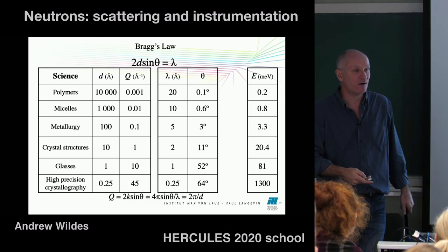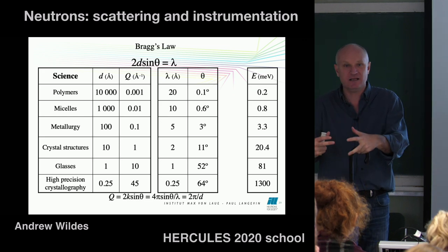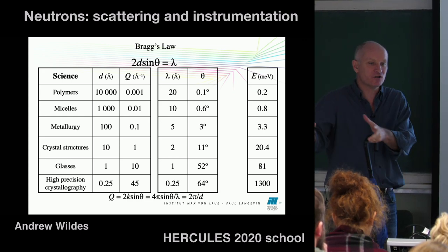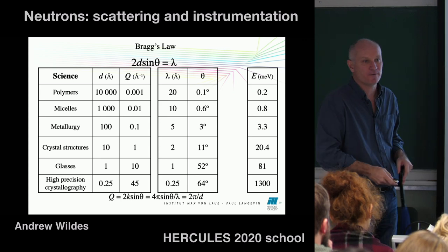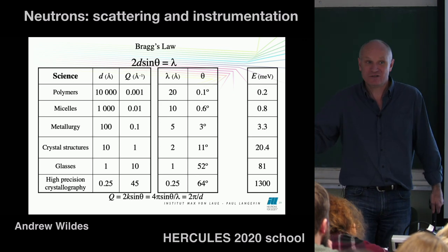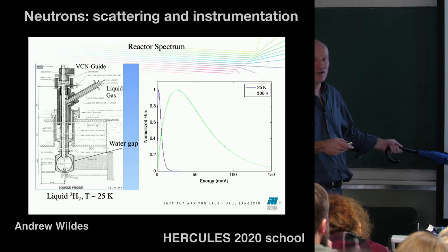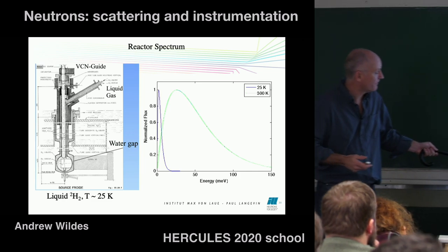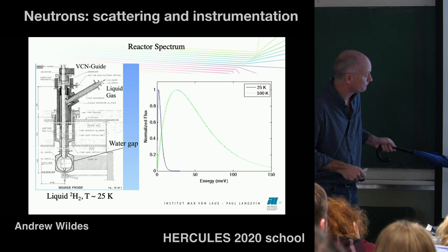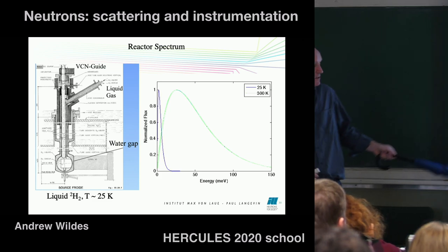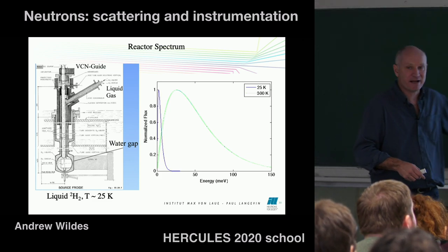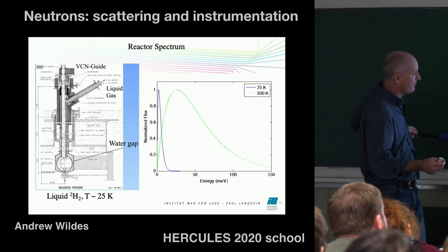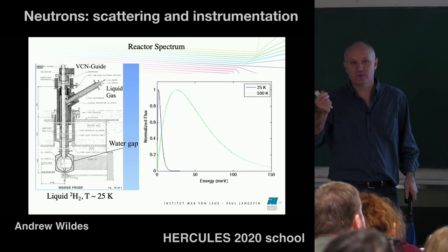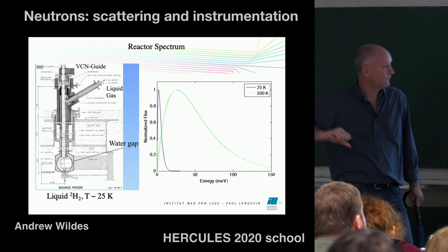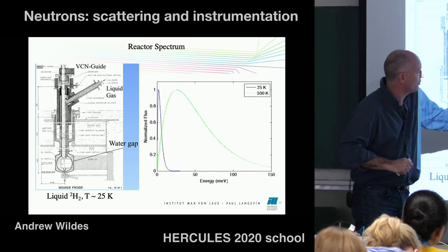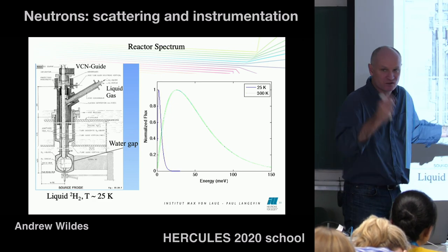So in order to get around that, we've got things that are called inserts. They'll sit inside the reactor, and they're designed to shift this flux to higher or lower temperature. And they are literally different temperatures. So one of them is called a cold source, right? Cold source, we've got two at the ILL. The cold source at the ILL is this liquid deuterium. It's held at about 25 Kelvin. And the neutrons that come into that rattle around inside this liquid deuterium, and they get cooled down. They lose energy. So what you get then is your Maxwell distribution gets shifted to much smaller energies.